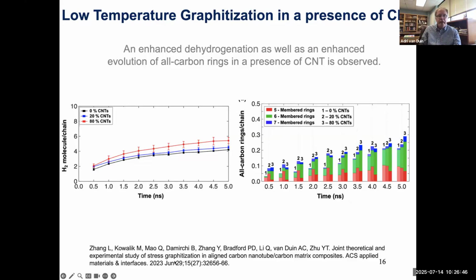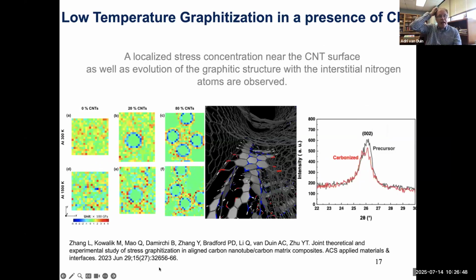So this was published in 2023. Our analysis shows that indeed the presence of the carbon nanotubes adds a local strain in the material. And even though that strain may not look like much, it is enough to help the deposition of new carbon material. Here you see our carbon nanotubes. You see the carbon nanotube wall, and you see how the new growth happens very strongly parallel to those carbon nanotube chains.